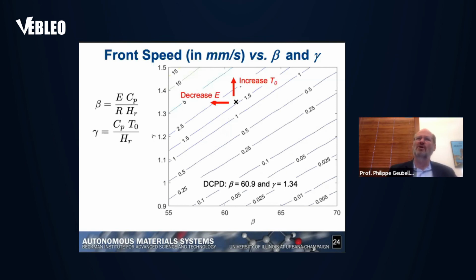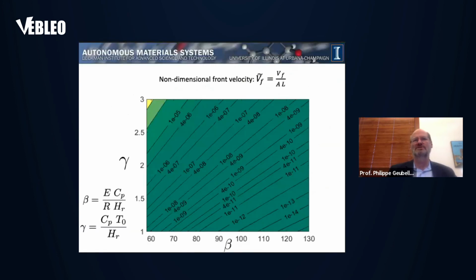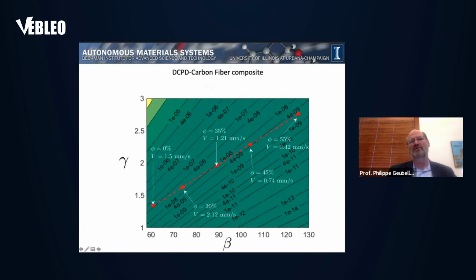We can also show that this particular approach, if we plot now the non-dimensional velocity, which is defined as follows, we can end up with a full solution that allows us to also look at the effect of the fiber volume fraction. So if phi is equal to 0, the velocity is about 1.5 millimeter per second. But as you increase the fiber volume fraction, you traverse this kind of space and obtain the speed of the front at different fiber volume fractions. So this is a very useful tool to really study different types of conditions.